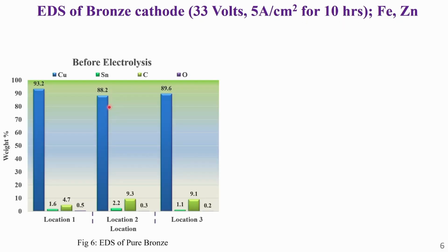This slide presents the EDS results of bronze alloy. We performed the experiment at 33 volt with 5 ampere per centimeter square current density for 10 hours. Figure 6 provides the EDS results of pure bronze that contains mostly copper in the blue bar and little tin in the dark green bar.